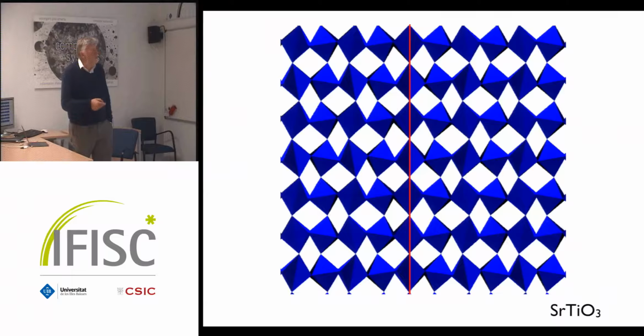You can also simulate that, of course. Again, the interface, here's a simulation of strontium titanate, these tilted octahedra. Here you tilt in one way, here you tilt in another way, and here's the twin boundary. Because they have to tilt to the right, they have to tilt to the left, and when the two come together, they can't tilt at all. They're stuck. It's a wrong structure, basically. And that's the thing of the functionality. The functionality comes when you have the wrong structure. And in a twin boundary, you always have the wrong structure, because you can't be right and left at the same time. So you have to combine these two to some new structure. And the new structure can have all sorts of things in there.